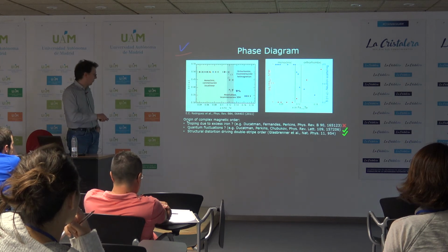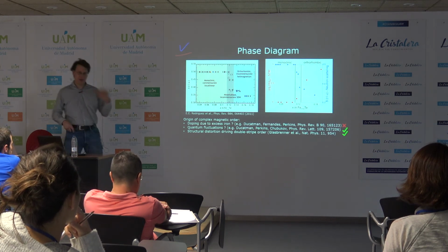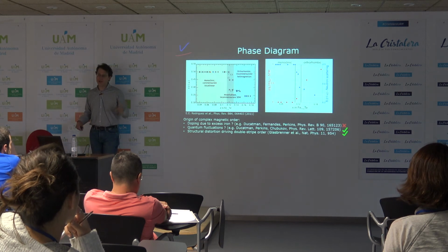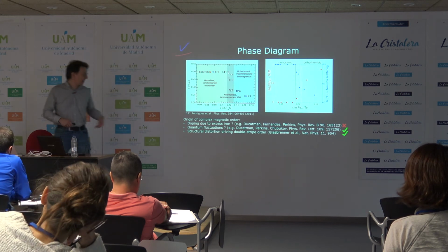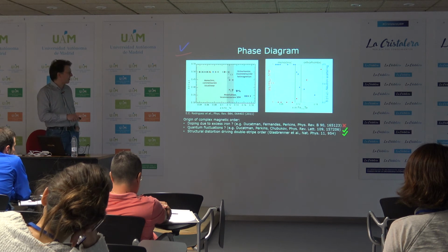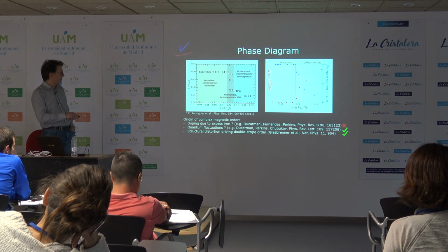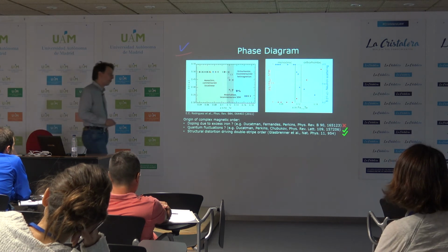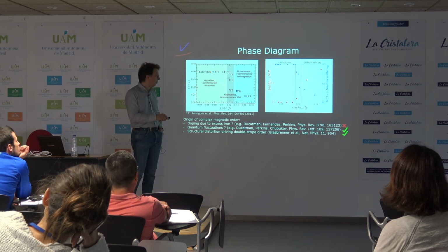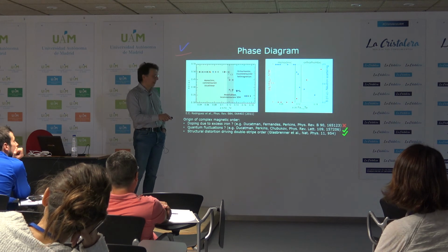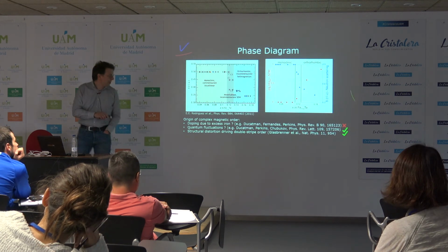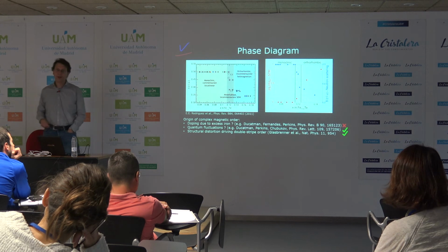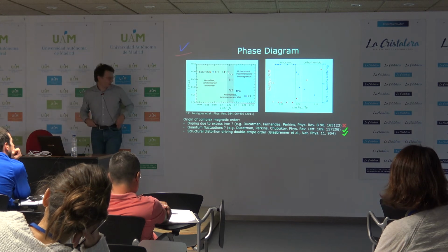I think from our data we can basically exclude that it's just a doping effect, if you like. Because if it was just a doping effect from the excess iron atoms, then by removing excess iron from the surface, we should always be able to go back to the bicollinear magnetic order, which is, however, not what we see. Right? If we remove the excess iron here, even in the high excess iron doped samples, we still see a plaid order with magnetic ordering in both directions.